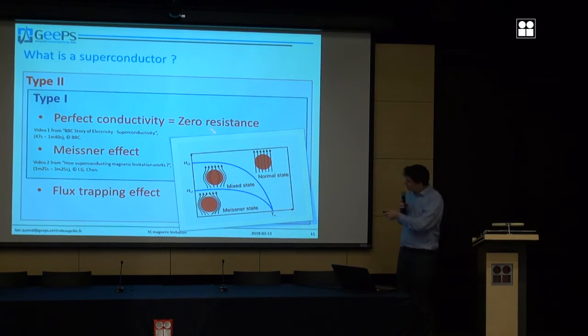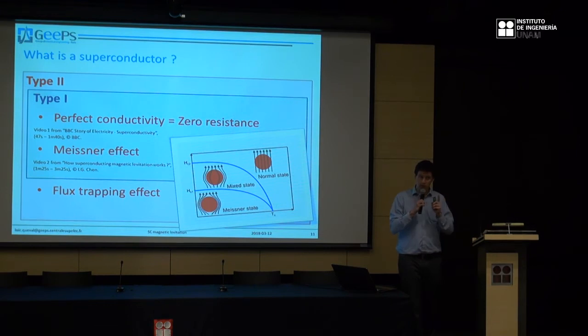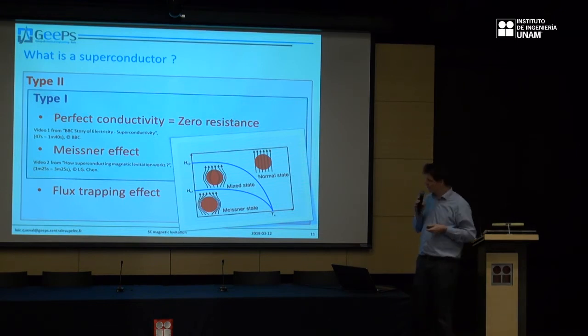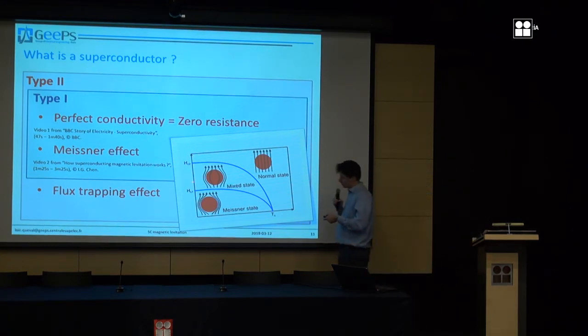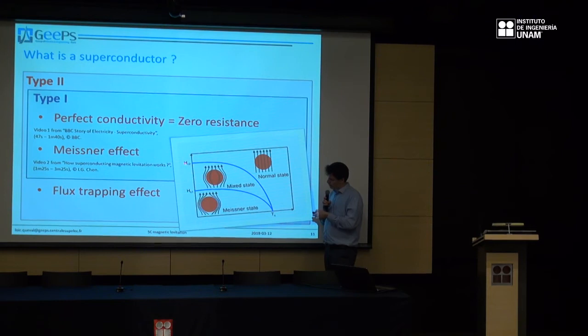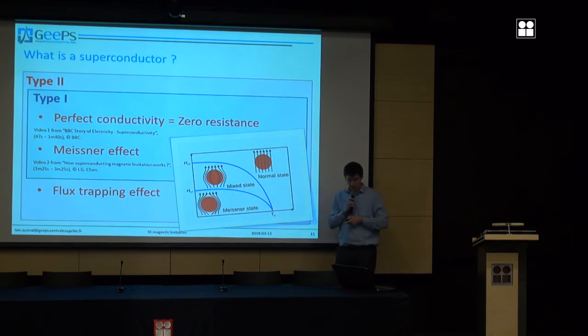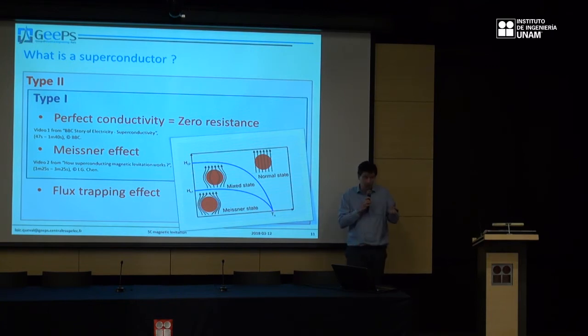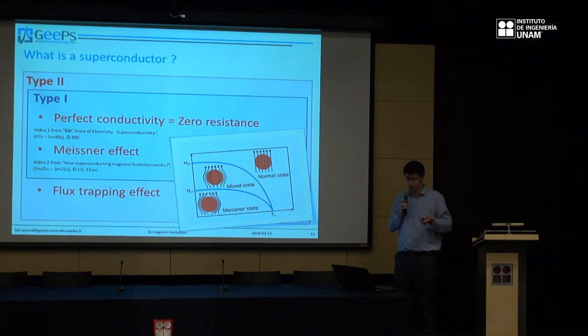So actually in between the normal and the Meissner state, the flux can enter one by one, a quantized effect, inside the superconductor. And this works only under a given field, and this is called the critical field, HC or BC. This critical field depends on the temperature, so it's a little bit complex to explain how it works. So if you want to be superconducting, you have to be below this field and below this temperature. If you have more field or more temperature, you are not a superconductor anymore.